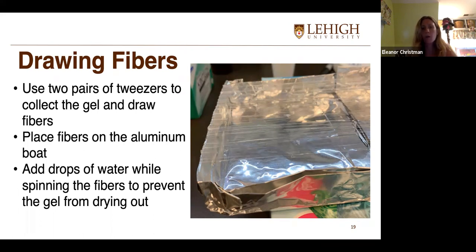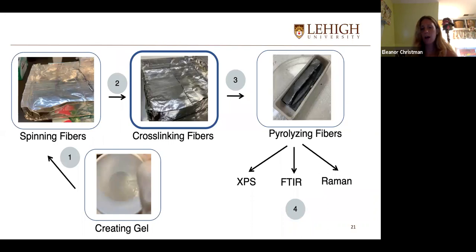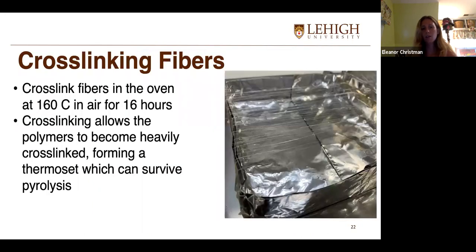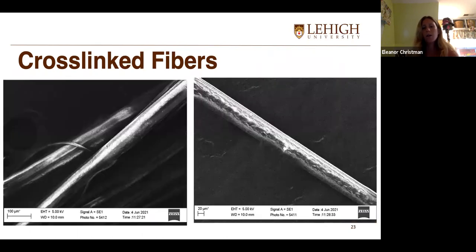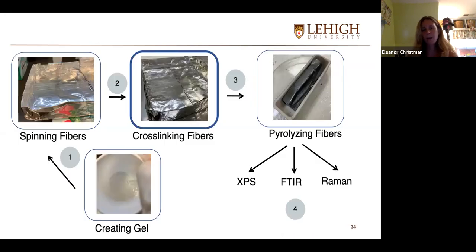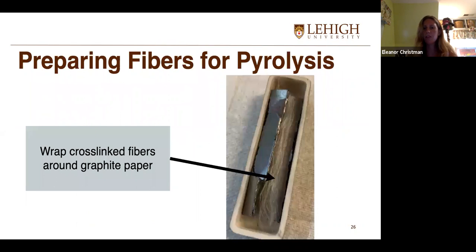drying out. So after spinning the fibers, I cross-link them in air at 160 degrees Celsius for 16 hours. The cross-linking allows these polymers to become heavily cross-linked, forming a thermoset so that they can survive the pyrolysis temperatures. And here are some images of the cross-linked fibers. And then from there, I move on to pyrolysis.